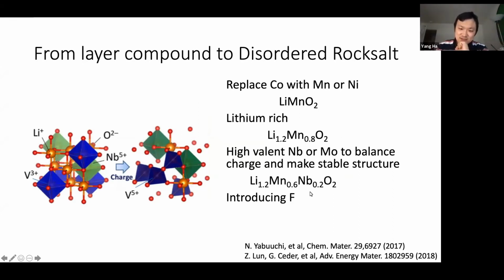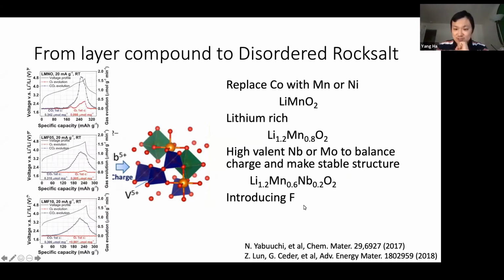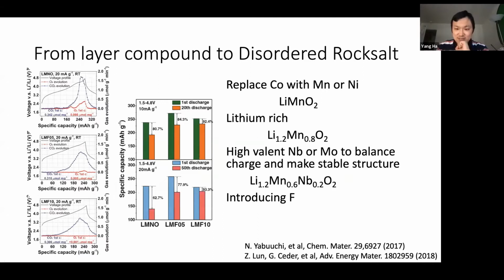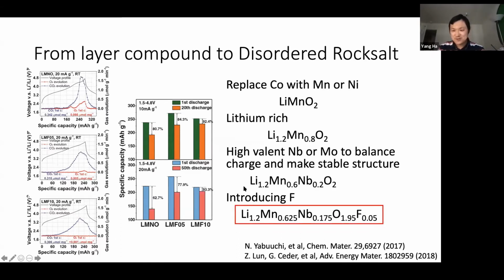So we can try to mix in more niobium or molybdenum. And interestingly, studies found that if we introduce more fluoride, we can increase the performance of our batteries. Here we see that when we have 0 fluoride and when we mix in more fluoride, we can suppress the release of the oxygen gas. And with fluoride, we can also increase the capacity and maintain the cyclability. The full mechanism of the fluoride is still not fully understood. We call it the magic fluoride effect, but we know we should try to mix in at least some fluoride in order to improve the performance. So this is how we go from our traditional lithium cobalt oxide to a somewhat complicated material like this.